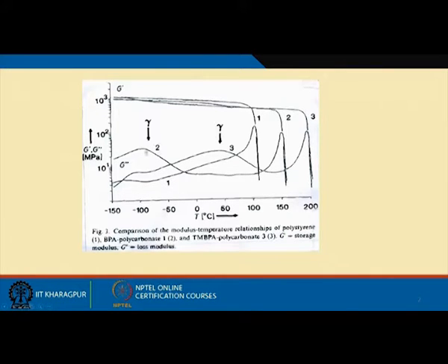So, there is still some motion in the chain, albeit a small number of atoms involved in that motion, much below glass transition temperature. If you think that everything is rigid below glass transition temperature, then think again, because this is not always true. Of course, at glass transition temperature maybe 50 or 60 atoms in the backbone together start to have all their motions freed up at a higher temperature, so that you have a big effect on G prime. But even much lower than glass transition temperature, you still can have motions.